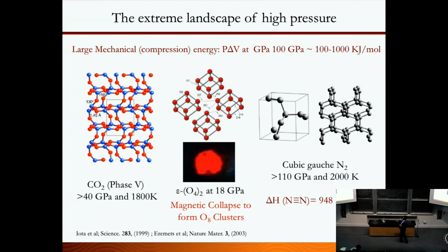And if you look at another example, nitrogen, one of the strongest triple bonds you have, almost 1,000 kilojoules per mole. It gives up this energy to go to a single bonded form. Starting with triple bonded nitrogen, it gives up that energy and goes to single bonded nitrogen. These kinds of transformations really fascinate me, why these crazy things happen under pressure. On the other hand, all the energy of the triple bond is now stored in the single bonds. So when you release it, you can get the whole energy back. So you are creating an energetic material, a high density material.